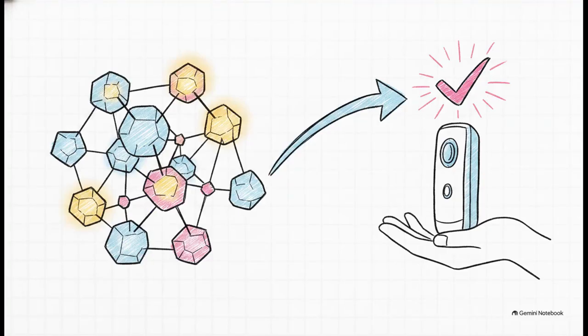To wrap this all up, our research conclusively demonstrates that doping tin dioxide with gadolinium successfully restricts crystal growth and creates highly beneficial structural defects, and those physical changes translate directly into vastly superior acetone gas sensing capabilities compared to using just the pure material. Out of all our tests, the gadolinium-doped film deposited for 90 minutes hit the perfect sweet spot, delivering the best overall performance, rock-solid repeatability, and incredible sensitivity. It's safe to say this material is a seriously viable candidate for the next generation of portable devices designed for non-invasive diabetes monitoring.